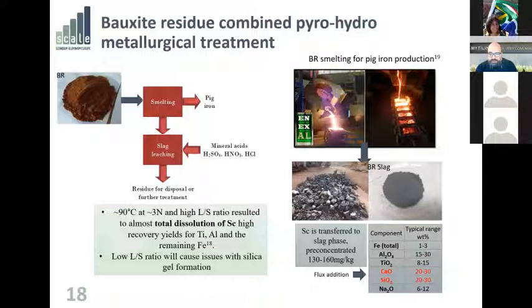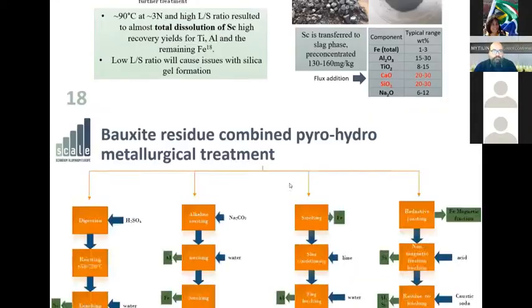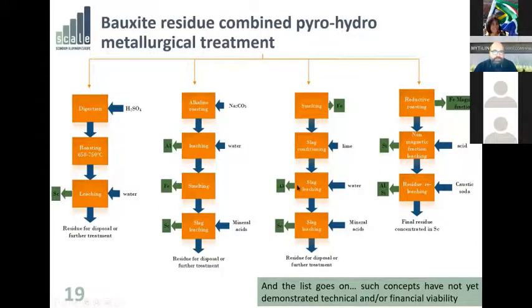You can see the slag produced from smelting bauxite residue has very little iron, but has very high calcium and silica, based also on the fluxes used during the pyrometallurgical process. So there are several variations of this idea, which is almost endless to track.